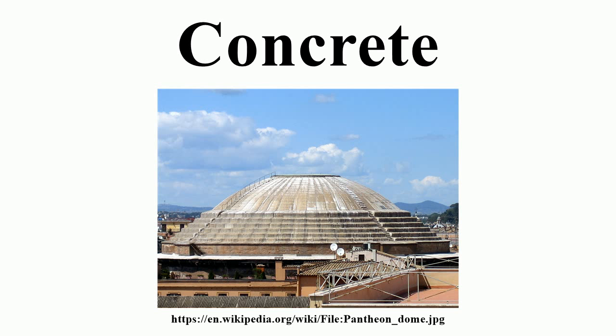Air entraining agents add and entrain tiny air bubbles in the concrete, which reduces damage during freeze-thaw cycles, increasing durability. However, entrained air entails a trade-off with strength, as each 1% of air may decrease compressive strength 5%. If too much air becomes trapped in the concrete as a result of the mixing process, defoamers can be used to encourage the air bubbles to agglomerate, rise to the surface of the wet concrete and then disperse.